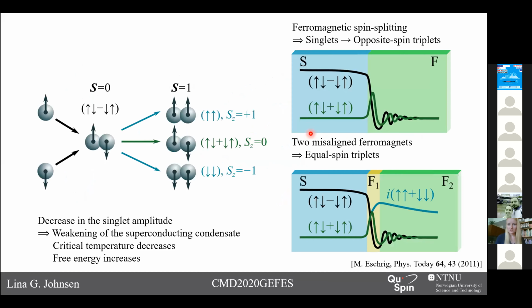So let's look at some systems where this happens. If we first look at a superconductor ferromagnet structure, where we just have one homogeneous ferromagnet, the spin splitting of the energy bands in the ferromagnets leads to a mixing of spin up and spin down, so that we get a mixing of the singlet and opposite spin triplet amplitudes. However, this system is invariant under rotation of the magnetization in the ferromagnet, and also both the singlet and the opposite spin triplet amplitudes do not survive for long distances inside the ferromagnet, since the spins try to align with the magnetization and they're opposite in the first place.